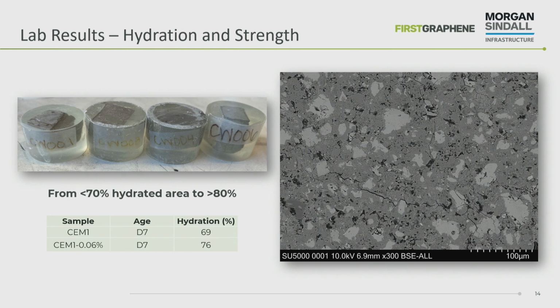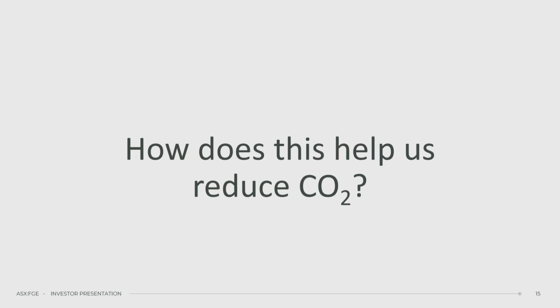We worked with Nick Winters, I don't know if you know him, but he looks at SEM images of cement from cement plants all across the country, and we used his guidance to try and identify what areas were the hydrated areas and monitor them. So basically we were looking at the improvement in hydration with the graphene addition. With standard SEM samples, we were getting about a 69% hydrated area, and with all samples containing graphene, there was always an improvement in the hydrated area percentage. So we think that's why there's these improvements in strength. One, because of the nucleation effect, but two, because these nucleations are happening on particles with very high tensile strength. So that's why we think this is happening. So how does this help us reduce CO2?